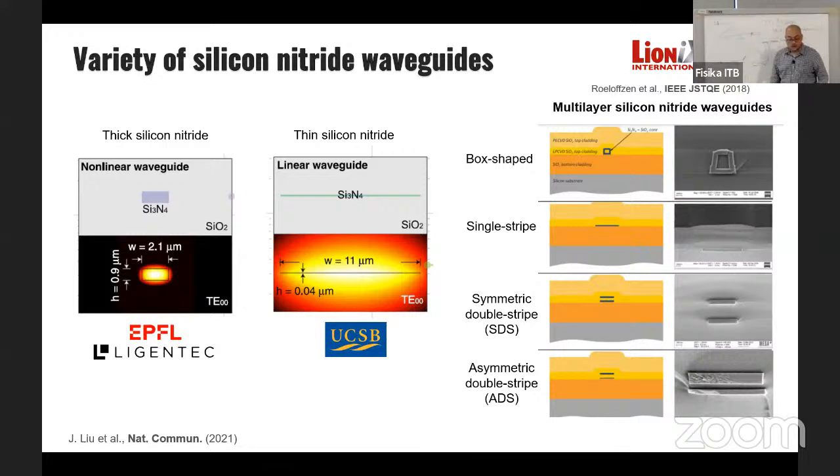So that is a problem that is being solved by many, many people these days. What they do, again a bit hand-wavy, as far as I know, to solve this problem: let's say you have a wafer like this. This is just a top view, and the side view, of course, is the silicon oxide on the silicon wafer, and then you want to put silicon nitride on top of this, right? What they did is that they deposit silicon nitride until 300 nanometers, right? And then they turn the wafer. And then deposit, and then they turn the wafer.